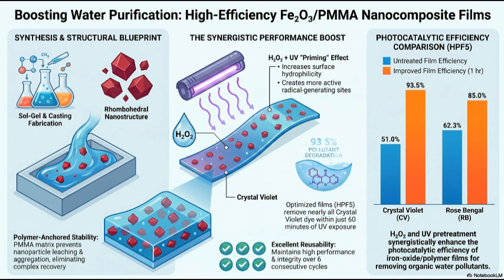But wait, if we are breaking down the polymer chains with UV and peroxide, aren't we just degrading the very shield we built to protect our nanoparticles? How does the whole thing not just fall apart in the water? It's a delicate balance. The hydrogen peroxide oxidizes the functional groups of the PMMA, specifically the carbonyl groups. Concurrently, the prolonged UV exposure causes photochemical chain scission. It literally severs the polymer chains on the surface and creates new, oxygen-containing functional groups.